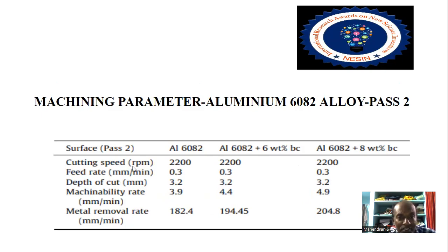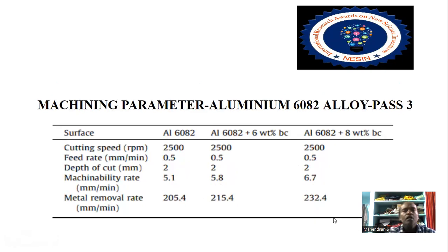And also, cutting speed and feed rate is increased. Machinability rate is also increased 3.9 to 4.9 and metal removal rate from 182.4 to 204.8 millimeter per minute. Next also, in another set, machinability rate is increased from 5.1 to 6.7 millimeter per minute. Metal removal rate 205.4 to 232.4 millimeter per minute. These are the various machinability rates. The metal removal rate also increased.